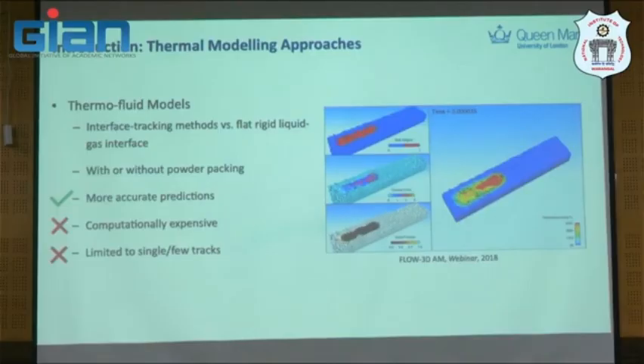Instead of that, this one is a thermal fluid model, and it uses an interface tracking method versus a flat rigid liquid-gas interface. With or without powder packing, it still provides some insight at the scale that we mentioned earlier, the defect scale, because porosity is a process defect, as are the microstructure and the roughness. So it's impossible for the previous model to predict it. It's a more accurate representation, or prediction, but computationally expensive and limited to very few tracks. That's because it's limited by the computational resources you have. But now probably you can print about 5 to 10 layers without any issue.